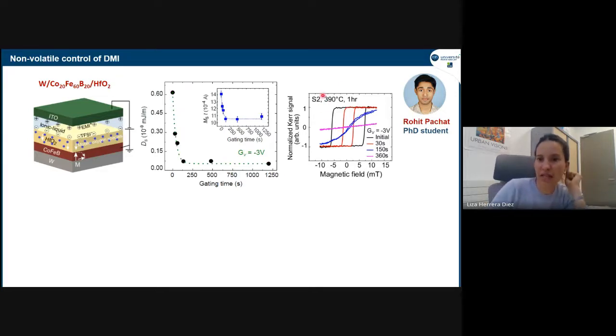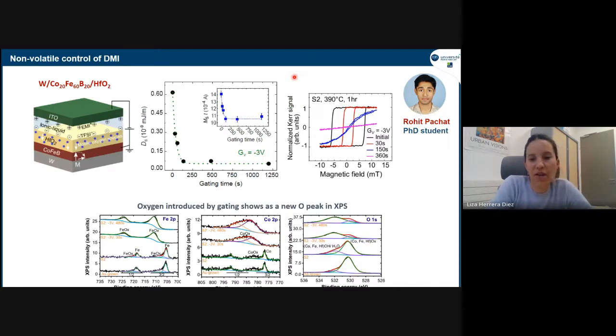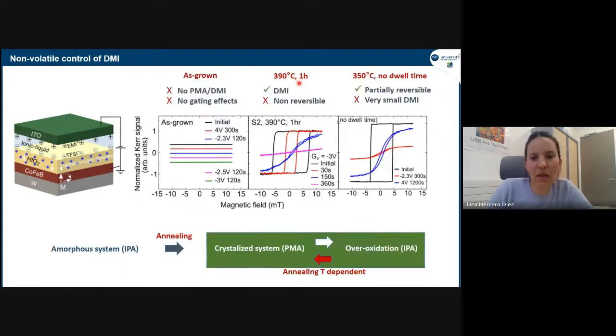So then we have to start from an annealed state, which is this black curve, and then we can bring it back to the in-plane anisotropy as we did with all the systems, as you can see before. Sorry, this is the system that I showed you before, the XPS. We can see the oxidation of the iron, of the cobalt, and the growth of a peak of oxygen after voltage application. So this is what I was trying to explain before.